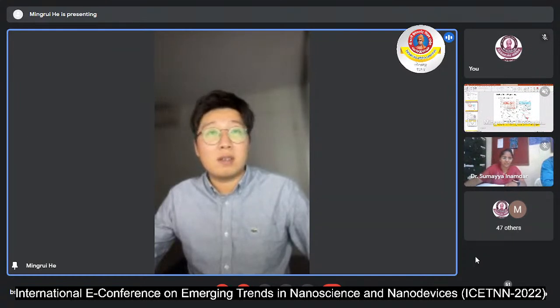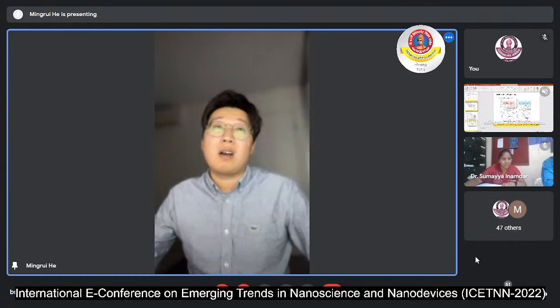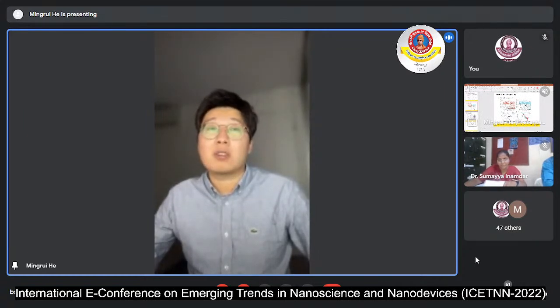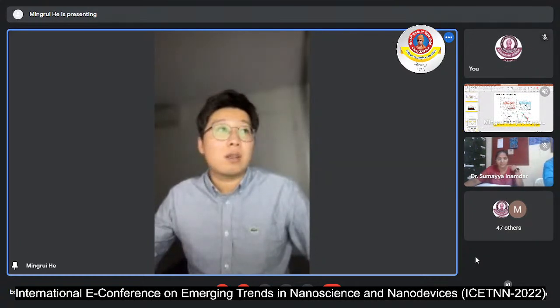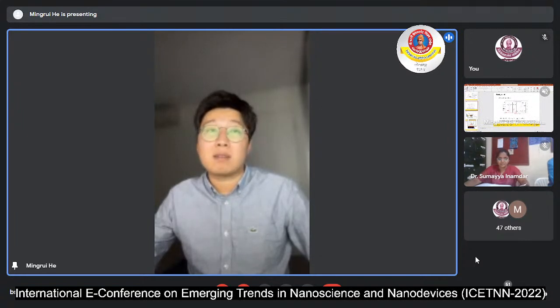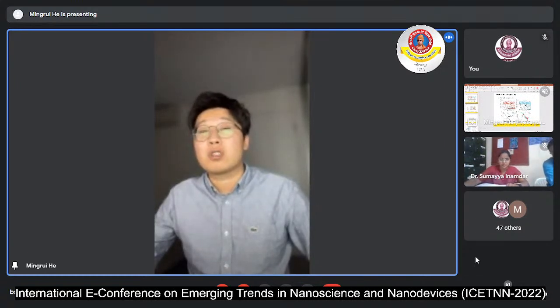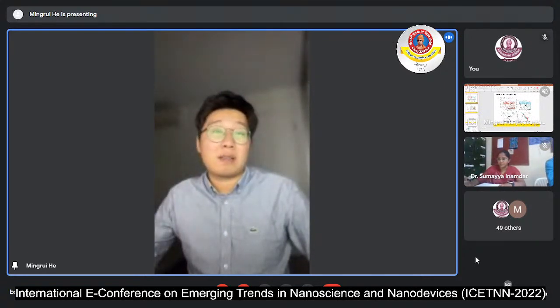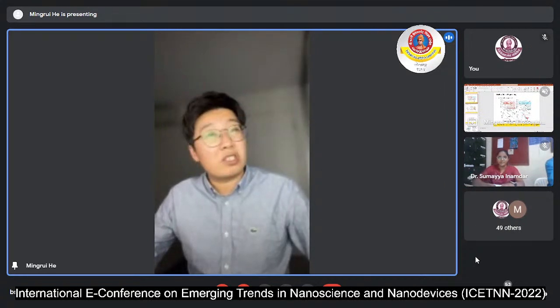The reference sample without lithium shows the shallow defect, which corresponds to the copper-zinc antisite defect, as calculated by DFT. After doping the lithium, it changed to a more shallow defect, around 90-something meV. But there is no literature or calculation about which defect gives this kind of lower level.